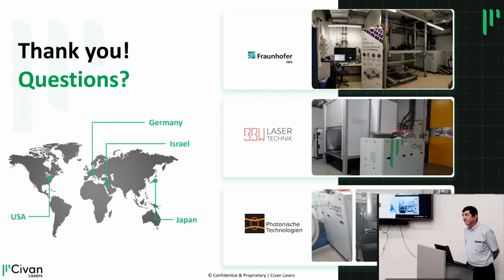Is there any relation to the plasma? The ionization rate in the plasma that's created in the keyhole. Okay, I don't have these numbers in my head, but we did look a lot into it, definitely in the simulation stage, to make sure that when you have deep penetration, the plasma doesn't stop the laser. So it's definitely an issue, and being able to keep the keyhole open and get rid of the plasma is critical. Otherwise, when you get to too high power and deep keyhole, the plasma basically blocks the laser. So I don't have the numbers, but it is an issue that we had to deal with here.